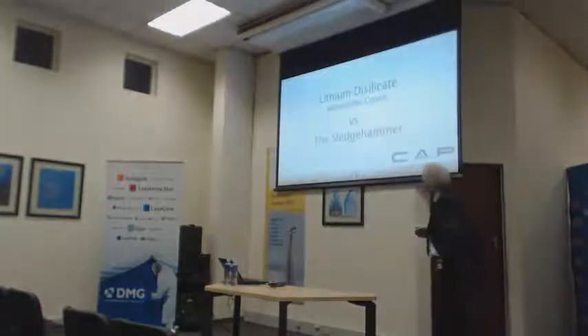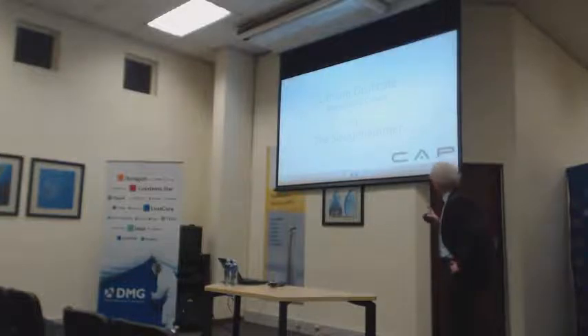Now, doing that same experiment with a full zirconia crown. So same height, same sledgehammer, wham! We should work on the sound next time. Now, the one thing they're going to do here, and this is the new kid on the block, this is Emax, basically. Lithium disilicate. This is an in-between thing in strength between the glass ceramic and the zirconia. And that didn't survive either.